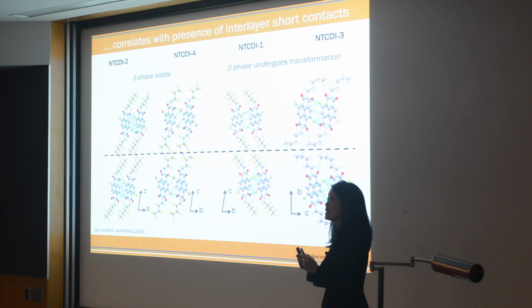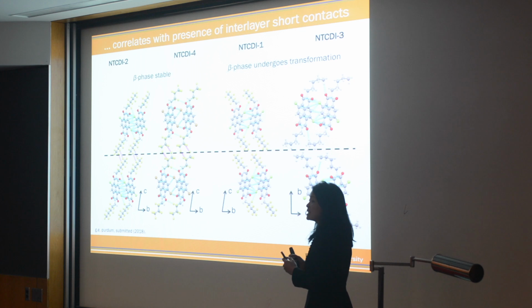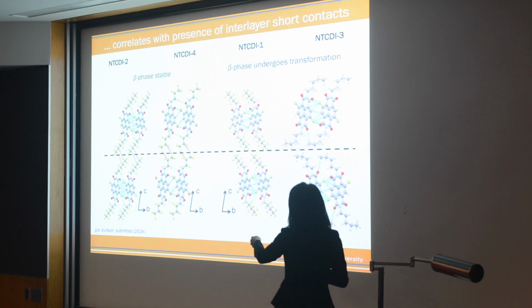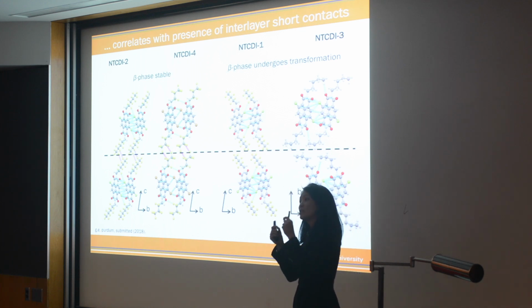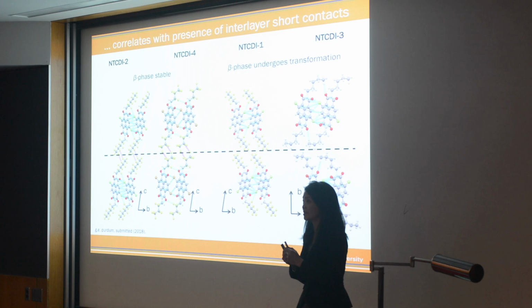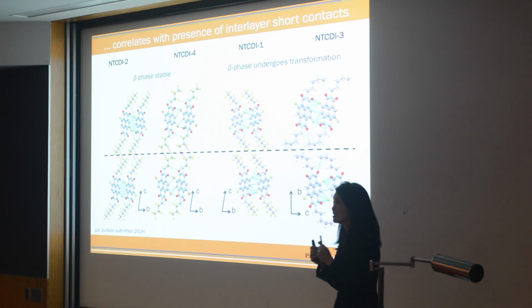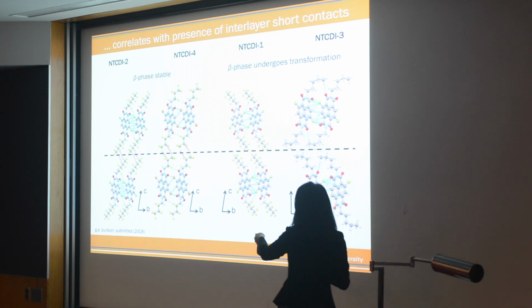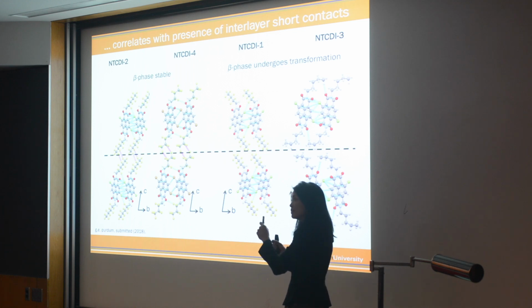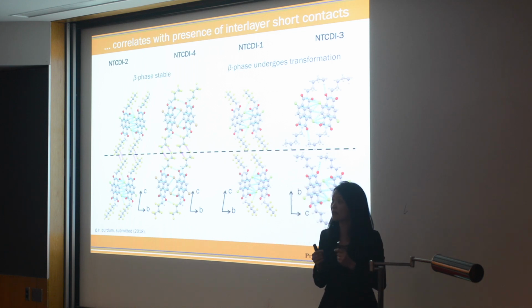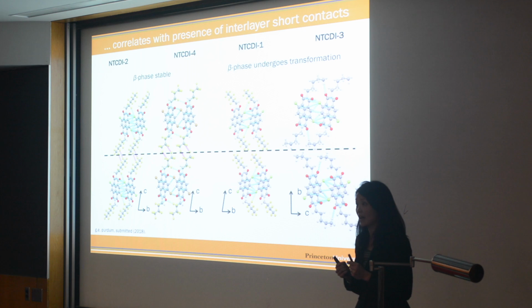So at this point, we need a framework to quantify what these short contacts are. And so we've used a very simple parameter that we call short interlayer contacts. That's basically the distance between the atoms on neighboring molecules minus the sum of the van der Waals radii of the same two atoms. Okay, so I'm going to say it again. It's the difference between the distance of the two atoms on different molecules minus the sum of the van der Waals radii of the same two atoms.